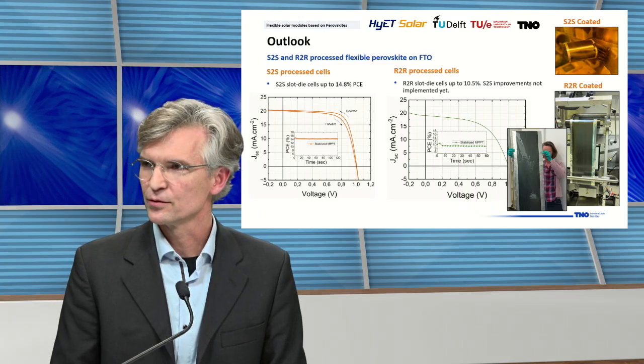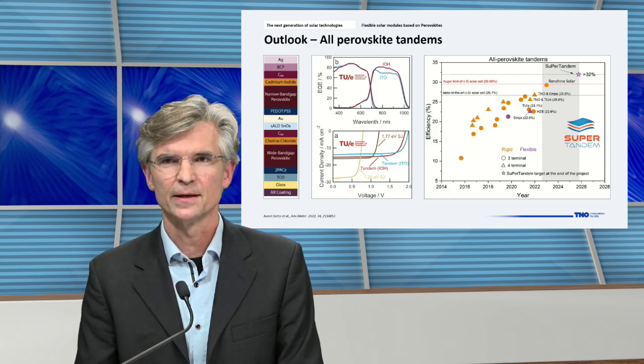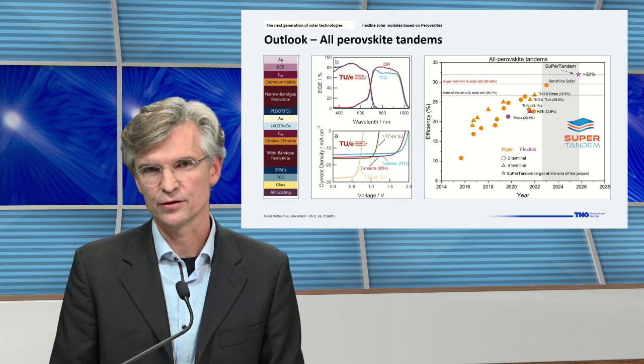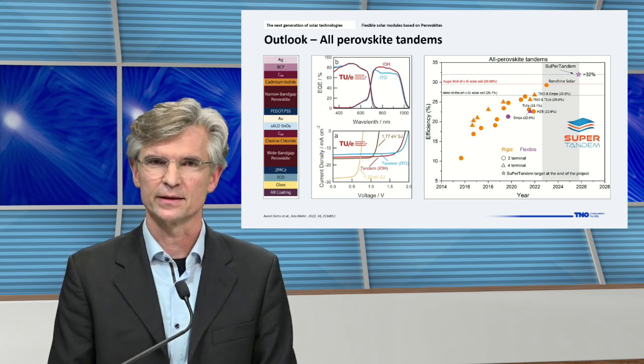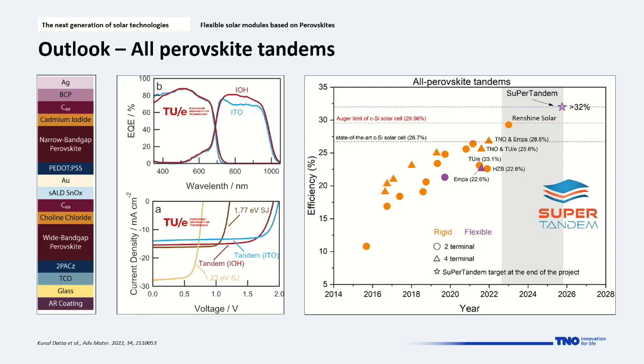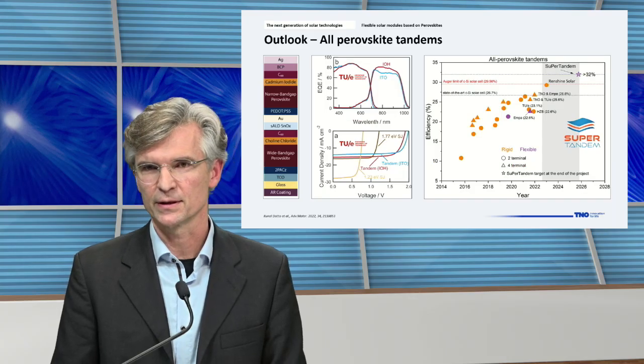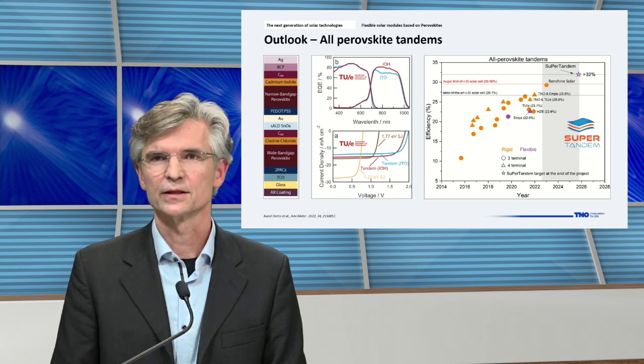Now it's also interesting to further look what can be done with this technology. You can stack 2 perovskite layers on top of each other and make a perovskite tandem device. And this has been done in close collaboration with the Technical University of Eindhoven, where we achieve an efficiency of well above 20%. And that can be pushed further, as indicated on the graph on the right-hand side, where we see that already devices have been obtained with close to 30%. TNO is actually also looking in this technology in the European project Super Tandem with many partners.